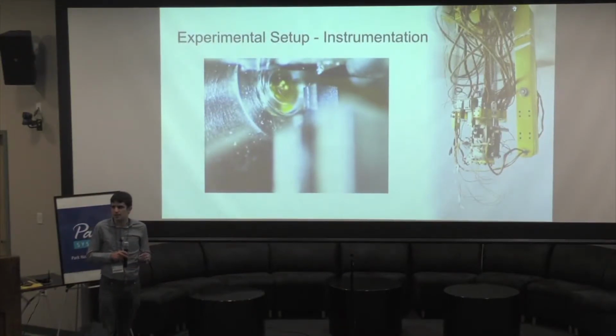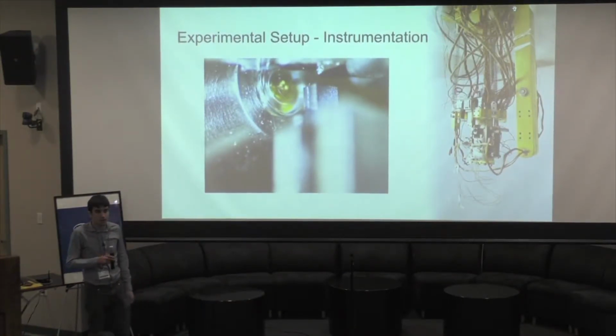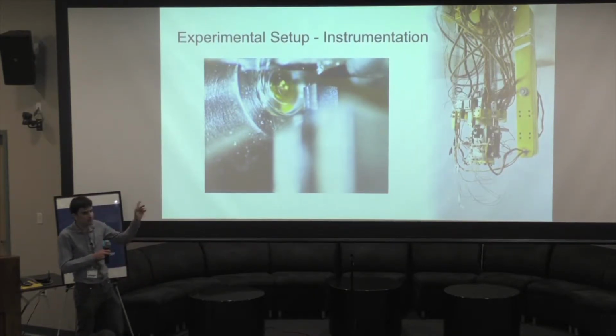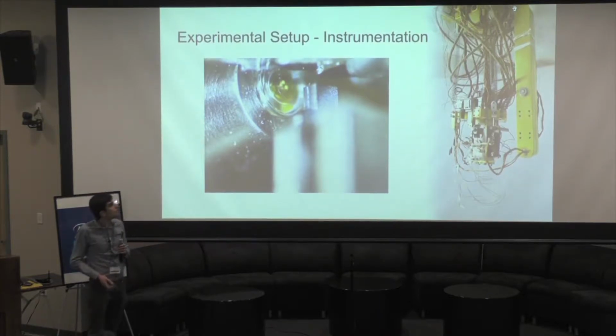The measurements were conducted in a home-built high vacuum scanning probe microscope. Coarse positioning is achieved by piezoelectric steppers, fine positioning by piezoelectric scanners. The cantilever's motion can be excited with the shake piezo and read out with a laser interferometer. On the image on the left, if you look very closely at the top, you can see the optical microscope view that we use to align the cantilevers to the sample.